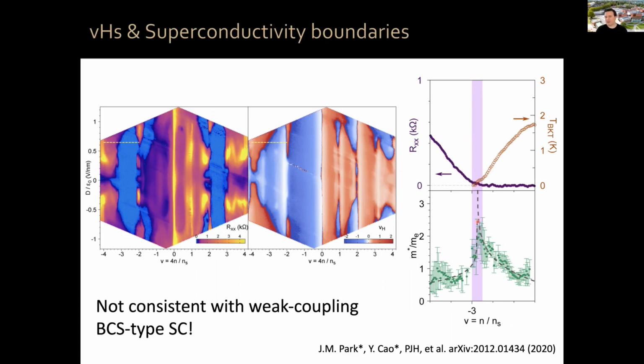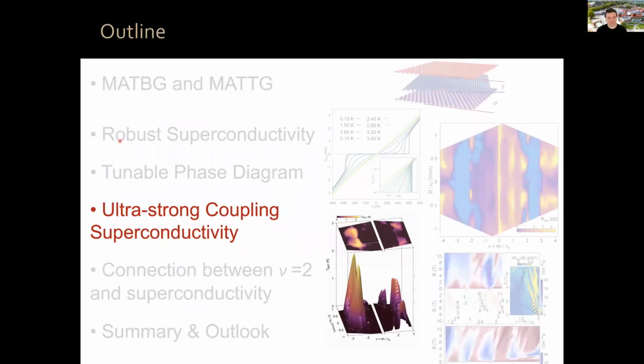And in fact, it ends your superconducting phase at the van Hove singularity, okay? This is very much against our intuition from weak coupling BCS type superconductivity, where high density of states leads to high critical temperature, okay? So not only does it decrease Tc as the density of states increases, at the point where it should be maximum, it's actually 0, and it's bounded, the superconductivity. In fact, that forms the boundary of your superconducting region, okay? I'll come back to this in a moment.